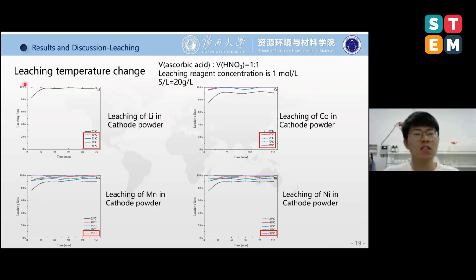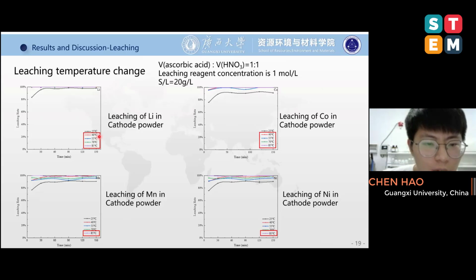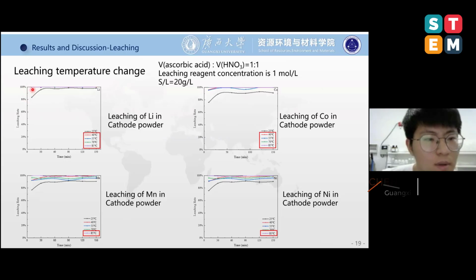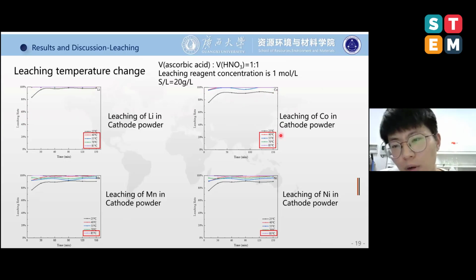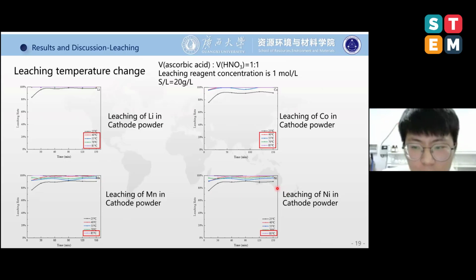Last, we investigate the temperature. The volume ratio is 1:1. The reagent concentration is 1 mole per liter, and the solid to liquid ratio is 20 grams per liter. For the lithium, at 40 degrees, we can get almost 100% leaching rate, and it is similar to the cobalt. For the lithium and cobalt, we can use the low temperature, but for the manganese and nickel, we can get almost 100% leaching rate only at the temperature 85 degrees. So we consider this phenomenon. We choose the highest temperature as the leaching temperature.